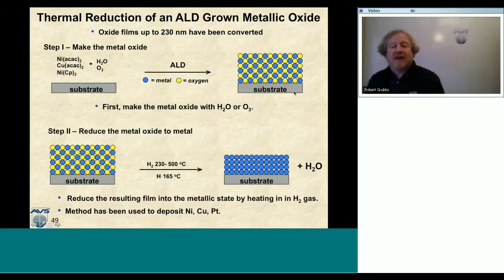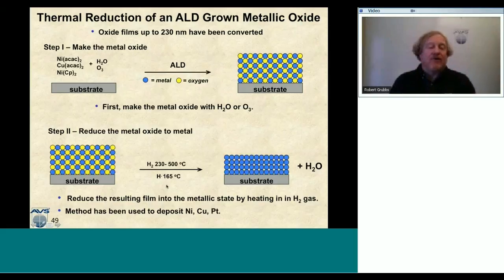So I make the metal oxide, and I take that metal oxide and stick it in a furnace with hydrogen, or I can use atomic hydrogen at a lower temperature, and I reduce all of that metal oxide down to the base metal. So it's not cheating in a way, but it is a way to make metals with ALD: you make the oxide first, and then it undergoes reduction to the base metal.